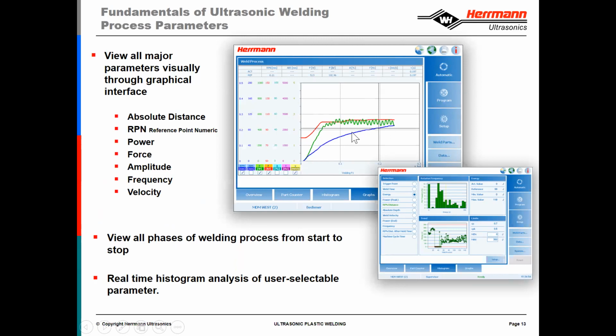I'd like to see at about this point, the curve continue on that upward trajectory. And therefore, what I would do is weld force 2 would have a little bit higher of a difference than weld force 1, and then potentially weld force 3 would have a higher application of force over weld force 2 as well. So that will influence the speed at which the parts are going together, which will result in this blue line being a little bit more linear. We also have some quality control things that we can look at statistically to see how in control the process is.